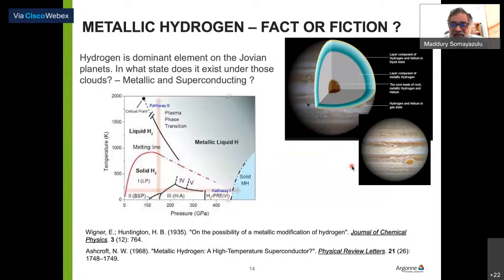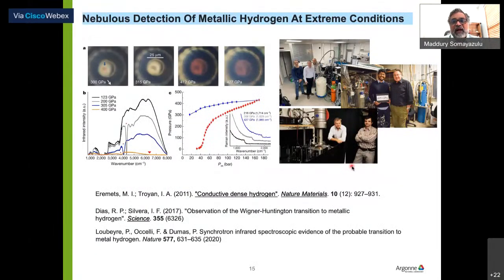In 1935, there was this intriguing paper by Wigner and Huntington, who predicted that hydrogen would become metallic with increasing pressure. Of course, the pressures at that time were marginal. People were not able to apply very high pressures, and what they thought was a very high pressure was about 30, 40 GPa, at which they predicted it would become metallic. Consequently began the quest for metallic hydrogen, which essentially drove high pressure physics to a large extent.